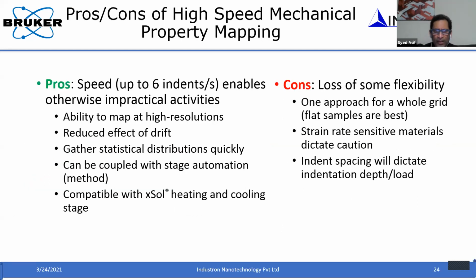So there are very big advantages of doing these very fast indents. First of all, because you're doing it at a very fast rate, the amount of time the tip is in contact with the sample is very much reduced. This is very important when you do high temperature measurements. Sometimes the tip reacts with the sample. When you do it in a very fast way, you don't allow that kinetic reaction to happen. You can prevent that.